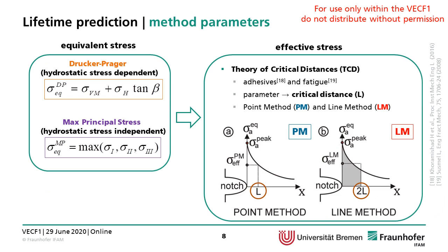Two equivalent stresses were used in this investigation. One is the Drucker Prager equivalent stress, which is hydrostatic stress dependent. So it has a component of the von Mises stress, but also has a dependence on the hydrostatic stress. The other is the max principal stress, which is hydrostatic stress independent, which is the maximum value of the principal stresses. To obtain the effective stress, the theory of critical distance was used.